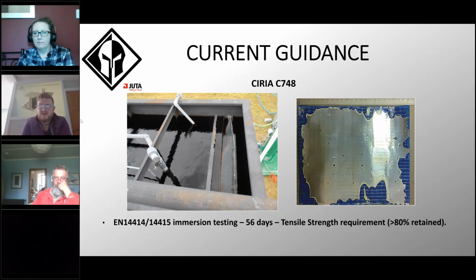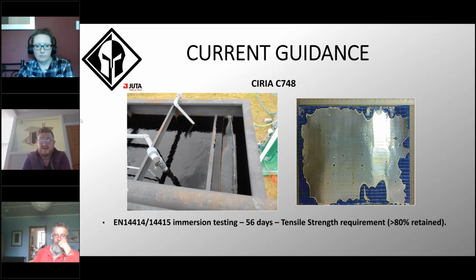An example here of an aluminium foil which has come out of an immersion bath. This is actually an alu foil coming out of an acid bath, and you can see the acid has actually stripped the polymer back and begun to attack the aluminium. So it's corroded around the scrim nodes of the aluminium foil. And again, this forms the basis of why we don't warrant the use of these materials in the application function, because we know they will fail over time. Yeah, it's a limitation of the material.